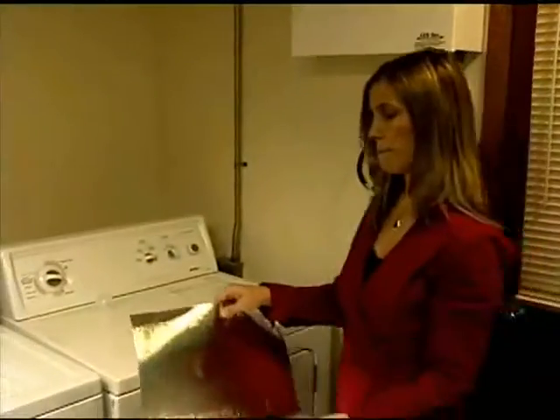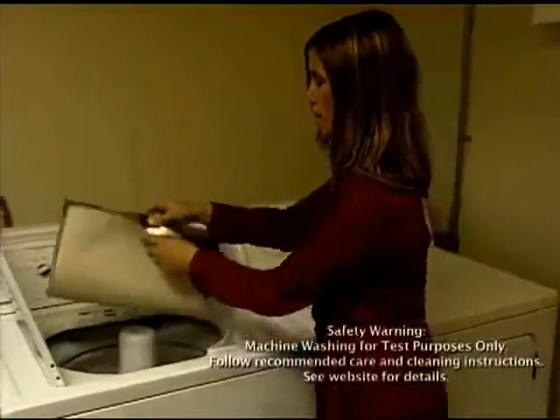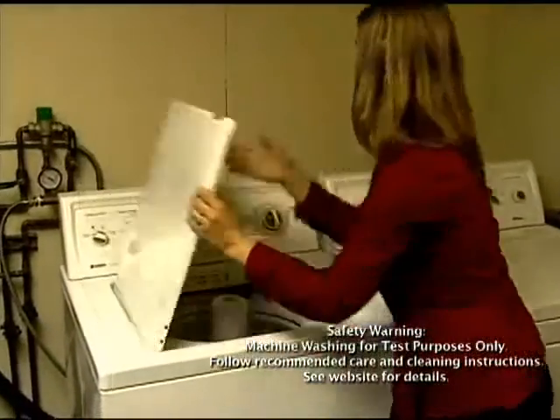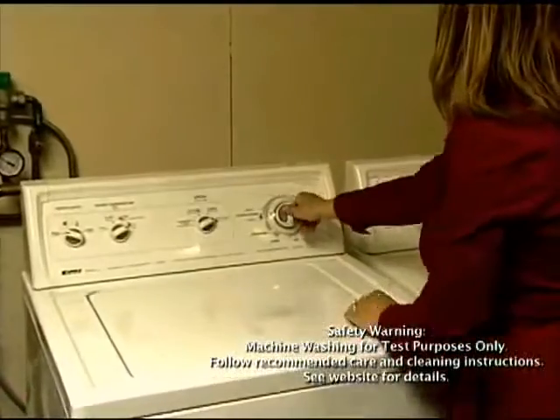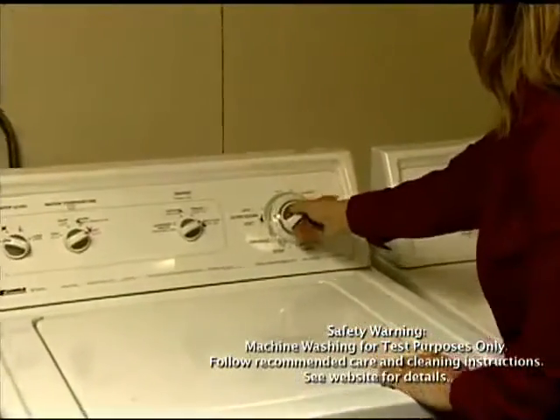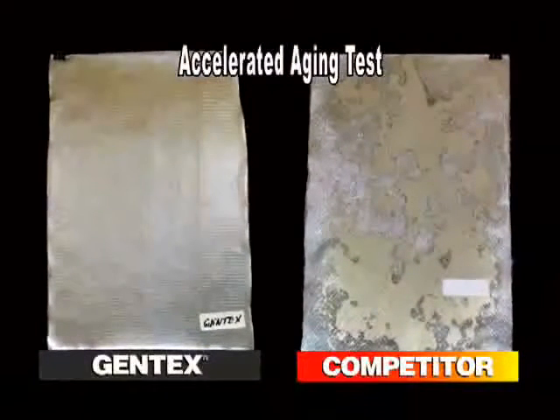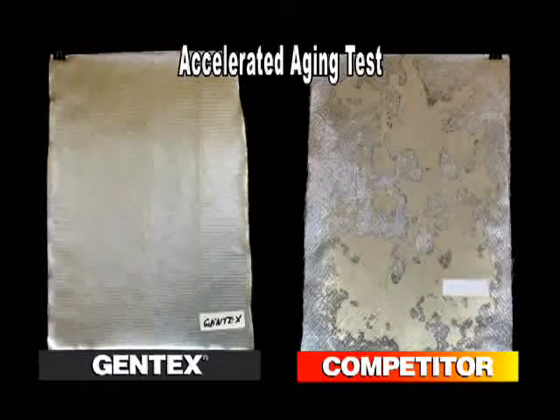The accelerated aging test is another routine test intended to predict long-term durability of the aluminized fabrics. This test, a commercial washing machine, is used to exert exaggerated flex and stress onto the aluminized fabric in a wet environment. No delamination of the aluminized film from the fabric is allowed. As you can see, the Gentex sample on the left does not exhibit delamination, while the competitor's sample on the right does, along with loss of aluminum and exposure of the adhesive layer after just one wash cycle. This is significant since routine performance testing requires the fabric to withstand 5 washes.